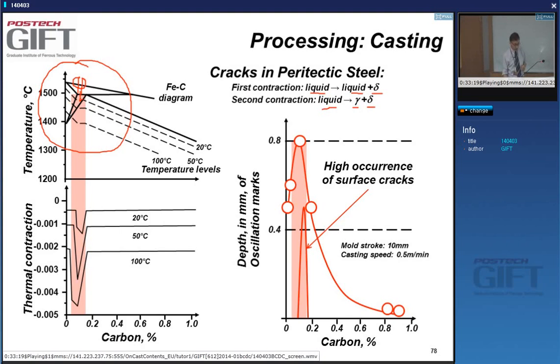And you can measure the thermal contraction. If you do the casting in this zone, depending on what temperature you look at, you do the solidification here, so you see this big contraction. And if you do the solidification at lower temperature, it becomes even bigger. Okay, so what does that mean?